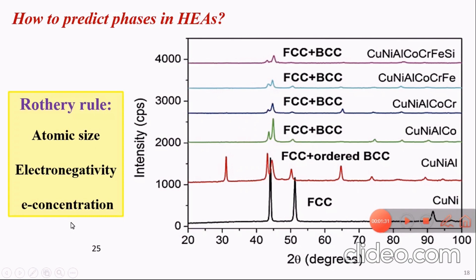Here we see the comparison between intensity and 2 theta, which are XRD patterns of different high entropy alloys. If we have only two elements, copper and nickel, we have FCC. If you add aluminum, you can have ordered BCC. If you add cobalt to the system, you have normal, regular BCC. If you add more elements, you can have different solid solutions.